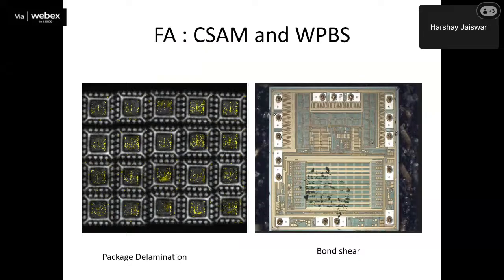And this picture you see is a CSAM, called a scanning acoustic microscope. This is the package, the same 3 by 3 millimeter package we have seen in the earlier slide. What we are looking for here: after temperature cycling, the package and the die are two different materials, and this can cause delamination of the package surface. So after this phase, we do this CSAM process to see if there is any uneven surface or not. If there is an uneven surface, it means a fail, because then the customer will have difficulty soldering this product in the real application.